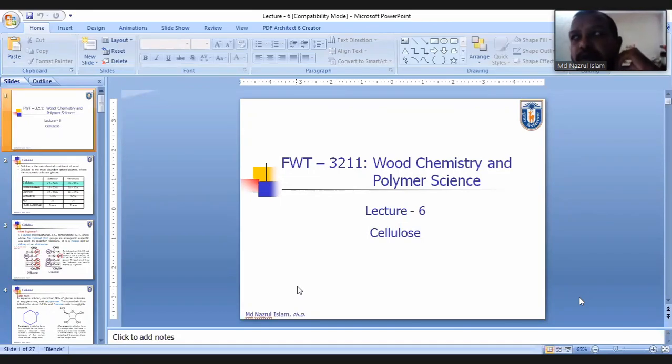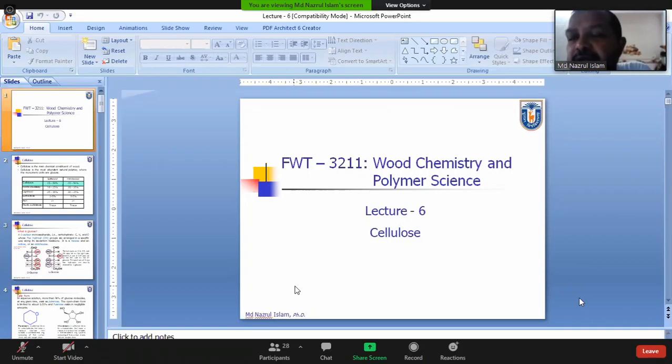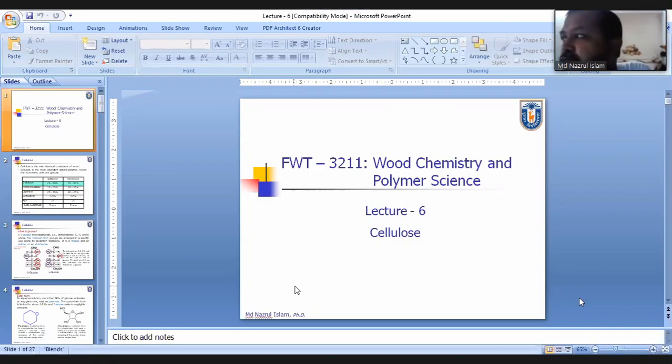So you have the cellulose and you are adding 17.5% sodium hydroxide solution, so that you will see some portion is dissolved and some portion doesn't dissolve. The portion that doesn't dissolve, we call alpha. And definitely there is sodium hydroxide solution, meaning it is alkaline. So you make the solution neutral, and you will see some precipitation. That precipitate portion, we call beta. Still some portion you cannot get, so that we call gamma.